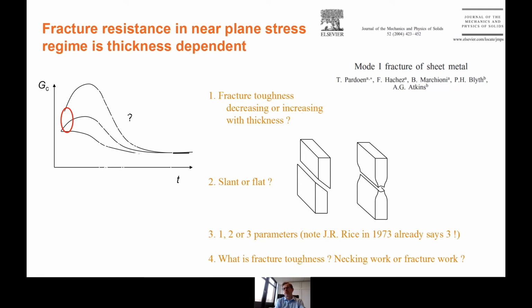And if you read textbooks, and papers by Broek, etc., you see curves like the one on the left side. You can find different curves. Sometimes what you see is, when you go from high thicknesses where the plane strain regime dominates and you have the well-defined J1C, and you reduce the thickness, you see that the fracture toughness increases. Sometimes it seems to reach a plateau and nothing else. But often what you see is that the fracture toughness increases to a maximum and then drops down.